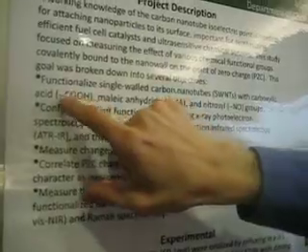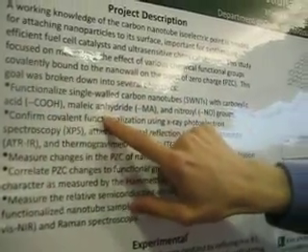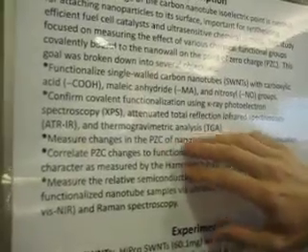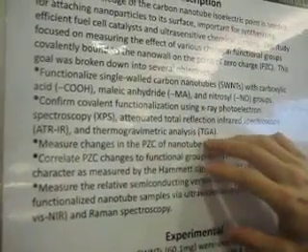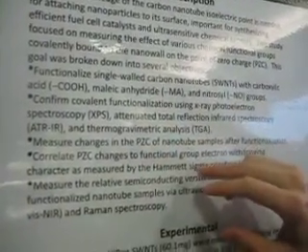For our study, we tried functionalizing them with carboxylic acid, maleic anhydride, and nitrosyl groups. We confirmed this using a variety of methods, such as XPS, ATR-IR, and TGA.